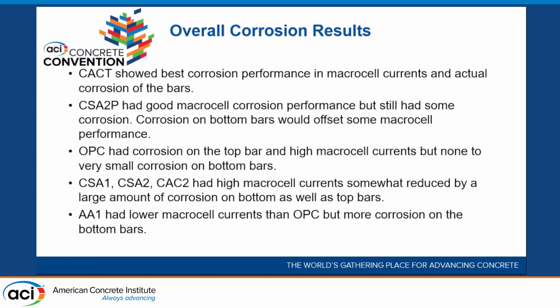So overall corrosion results is that we found out that the calcium aluminate cement with belite in it did very well corrosion-wise. The CSA2P had very good macrocell corrosion performance. Still some corrosion, and the corrosion on the bottom bars do offset macrocell performance. OPC had corrosion on the top bar, but no corrosion on the bottom bars. And the other ones had a combination of both.